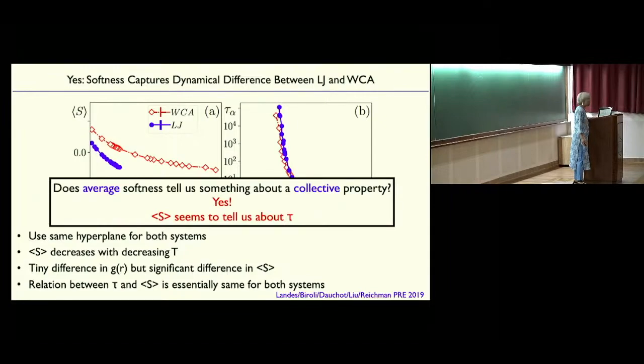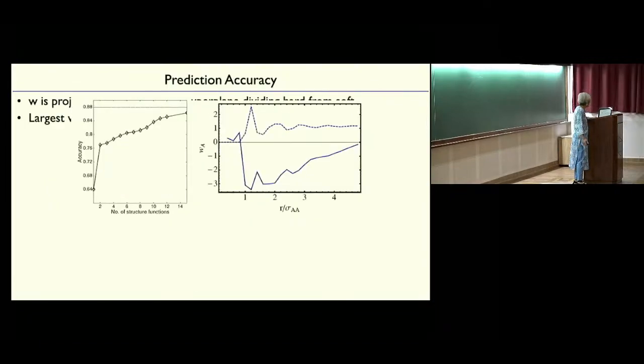So in this case, at least, the average softness seems to be telling us something about the relaxation time. That means we're on the right track. This could be the microscopic variable. To get back to Ranjini's question, it's pretty amazing: this is a binary mixture, so there are AA and AB for a central A particle. If you just keep the height of the first peak for AA and AB, just two of them, you already get over about 77% prediction accuracy. Then it just slowly gets better as you include more and more. It's not very sensitive, so once you go beyond a certain distance, it's really not going to change very much.